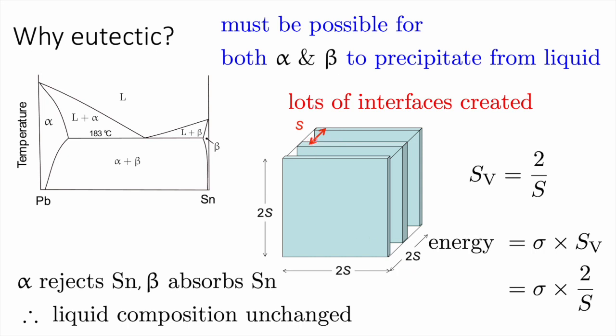limits the interlamellar spacing. So if your driving force for transformation is small, that means you're at a small undercooling below this eutectic temperature, then S will tend to be coarse, because the free energy cannot accommodate otherwise a finer interlamellar spacing. So if you want a finer spacing, then you've got to undercool the liquid much more below the eutectic temperature in order to provide the energy to create these interfaces.